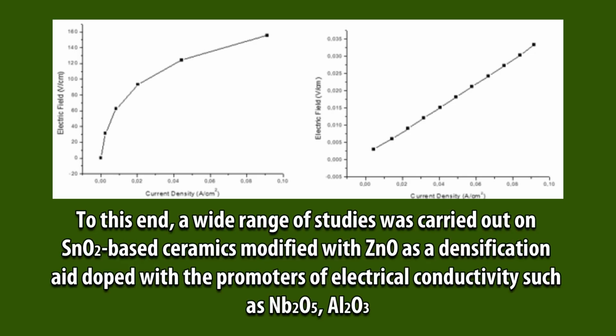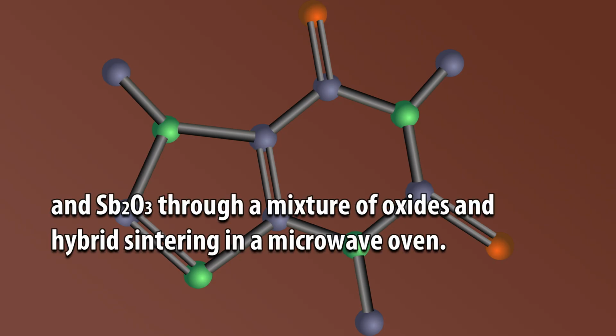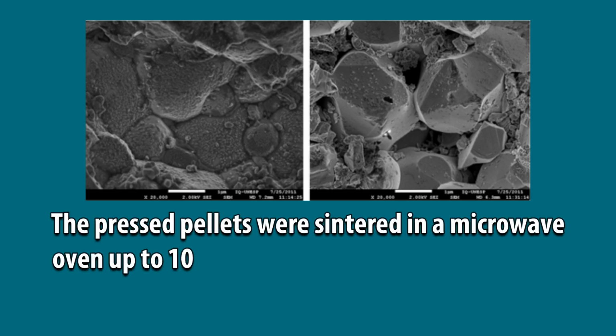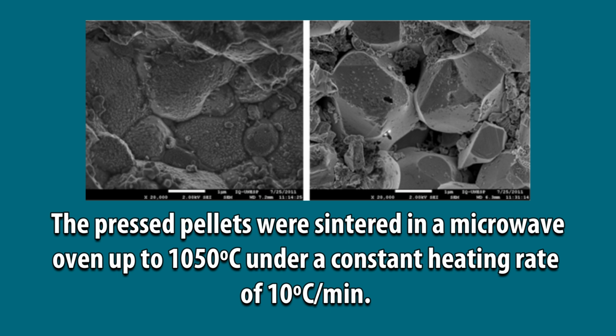To this end, a wide range of studies was carried out on SnO2 based ceramics modified with ZnO as a densification aid, doped with the promoters of electrical conductivity such as Nb2O5, Al2O3, and Sb2O3, through a mixture of oxides and hybrid sintering in a microwave oven. The pressed pellets were sintered in a microwave oven up to 1050 degrees Celsius under a constant heating rate of 10 degrees Celsius per minute.